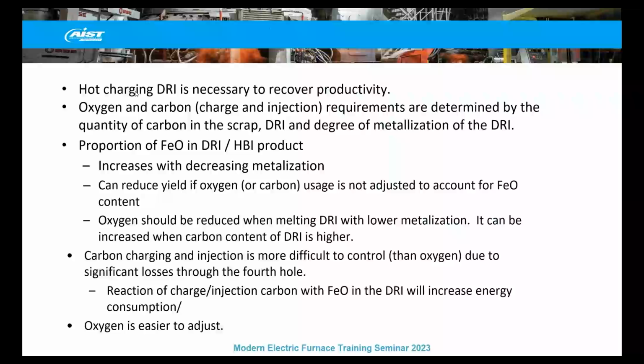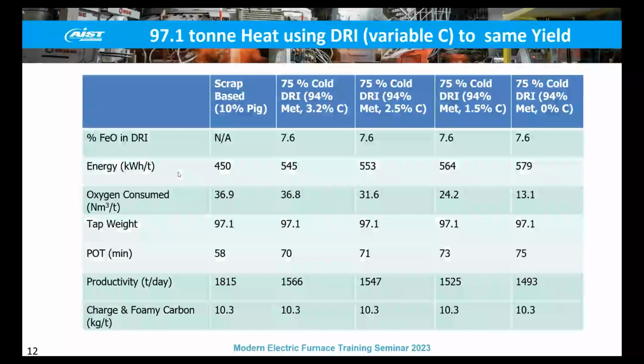These are some of his conclusions: hot charging DRI is necessary to recover productivity. The proportion of FeO in the DRI is important for looking at output of the electric arc furnaces. If you have high oxygen content, it will reduce your yield. So the quality of the DRI plays a significant role in the electric arc furnace.